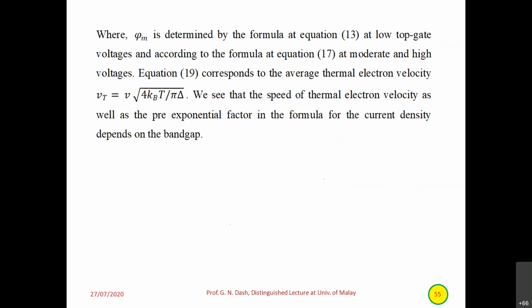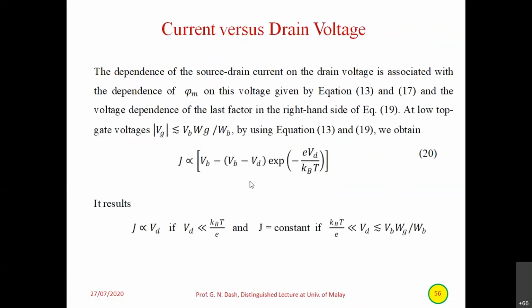You see that the thermal electron velocity actually enters as a pre-exponential factor in the current density, which depends on the band gap. Now, the current versus drain voltage: you can just make some manipulation, and this current is proportional to this. So this can be further analyzed: J is proportional to V_D if V_D is much less than this, and J is constant if this is much less than V_D. That means for low V_D, this is a linear relation, and for high drain voltage, we get a saturation region that is constant, similar to field effect transistors, as we already know.